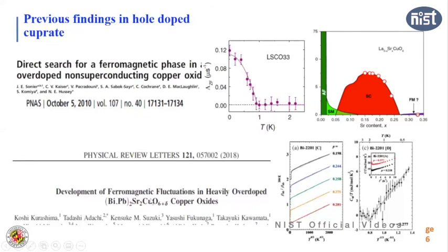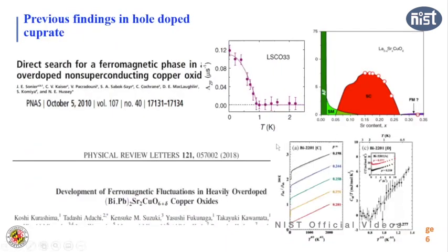Now, there are other recent studies also. This is another material, bismuth 2201. They also claim, in a paper published in PRL, that most likely there is a ferromagnetic fluctuation at the end of the dome. So what we learn is that all this data suggests that ferromagnetism is probably a universal feature of all these high temperature superconductors, meaning there is probably another ferromagnetic dome beyond the superconducting dome.